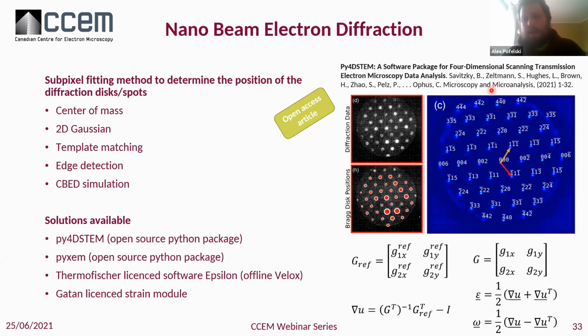Here I focus only on the strain aspect. That is using template-based matching, but also some more complicated mathematical approaches to make this Bragg disk position detection. So you have the diffraction data. This is a map showing the detection of the Bragg disks, and then afterwards they convert that into these types of maps where you have only single points representing the location of those disks.